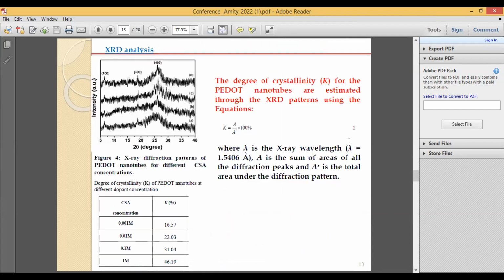And we have done XRD, and from the XRD pattern we have seen that no sharp peaks have been observed, so we can say that it's a semicrystalline material. From there we have calculated the degree of crystallinity, and we have seen that the value of K is found to increase with increasing dopant concentration. That means at high dopant concentration we have observed very well ordered nanotubes, that is, the polymer chains are very well ordered as the dopant concentration increases.